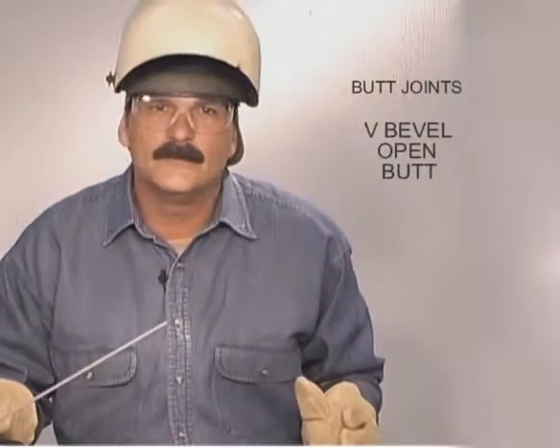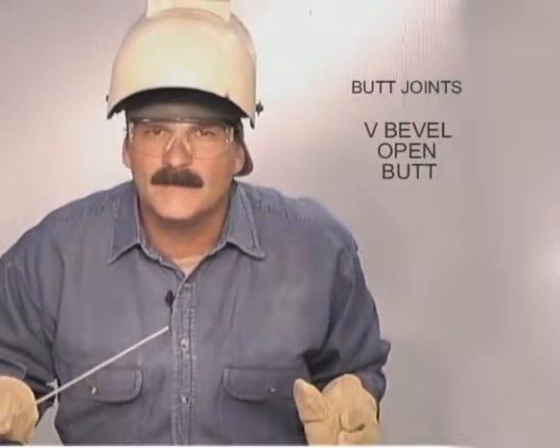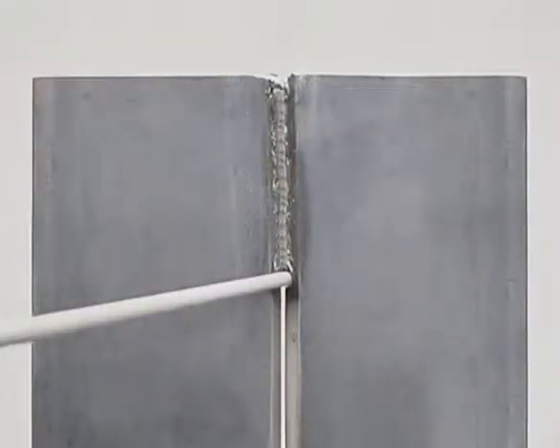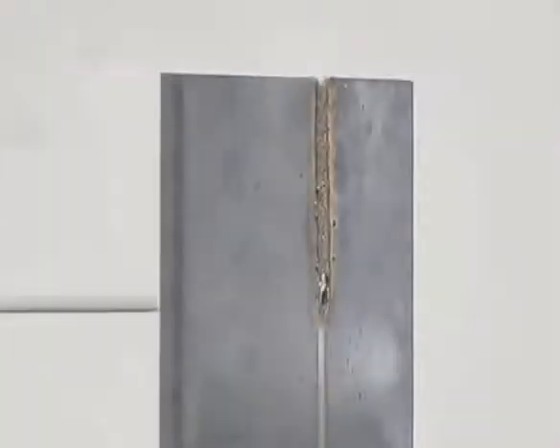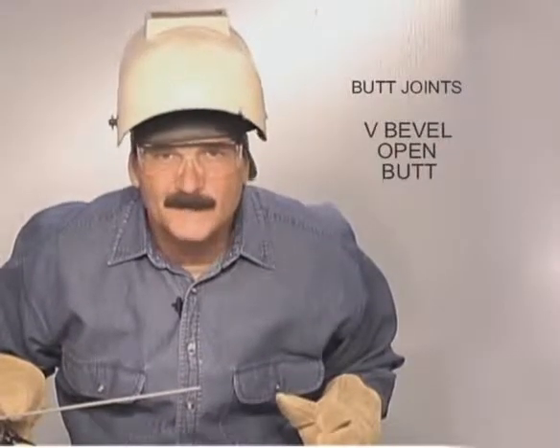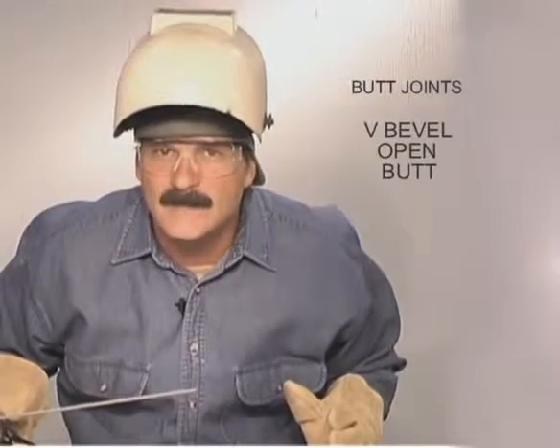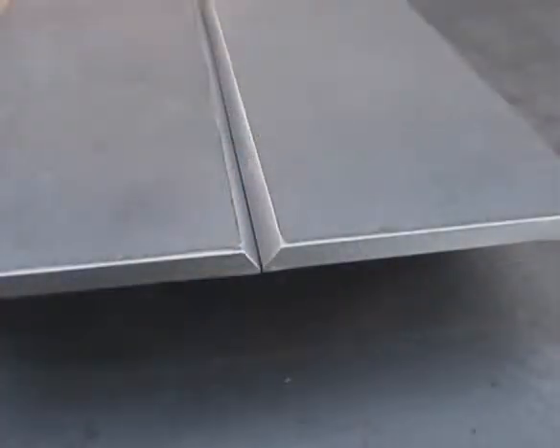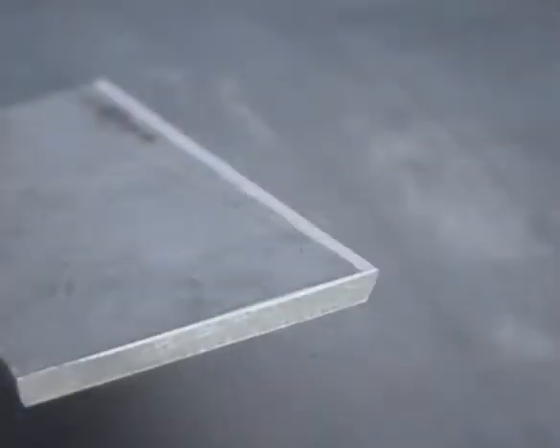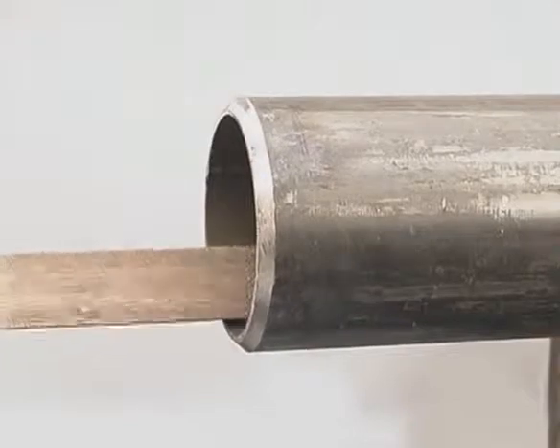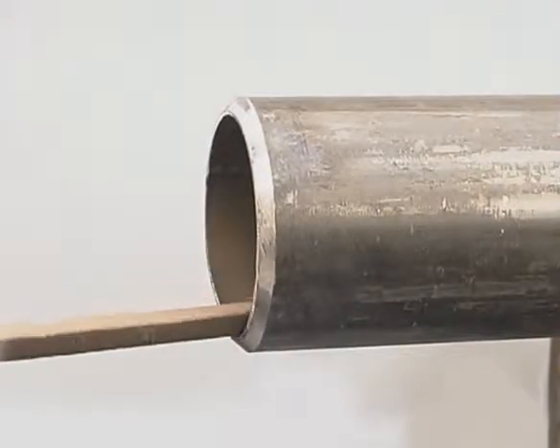The last type of root is in a V-beveled open butt joint. We're going to shove a 6010 rod deep into the gap and run a weld bead on the back side of the metal. Preparation and fit up are more critical, so take your time getting the metal ready. The edge of the bevel needs to be straight and square. Grind off all the mill scale on the bottom side. A half-round file works good to clean up the inside of square tubing or pipe.